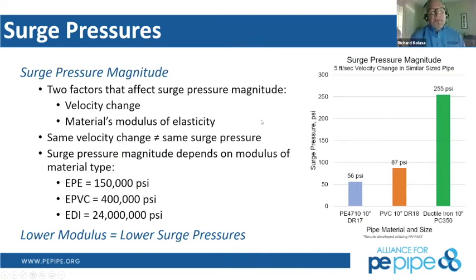So when we look at these surge magnitudes, for example, it's related to what the modulus of our materials is. When you look at these two factors of velocity change and the modulus of elasticity of the products, sometimes velocity change is not equal to the same surge pressure. And that's evident in the graph to the right, where we have surge pressure of a certain volume, but we also have the material type and size, where this modulus affects the magnitude of that surge event. You can see that because of the dampening effects of polyethylene on the lower modulus, you see a very low effect of the surge. So lower modulus actually equals lower surge pressure. If that's the case, then you're actually building an automatic safety factor into these products. Next slide, please.